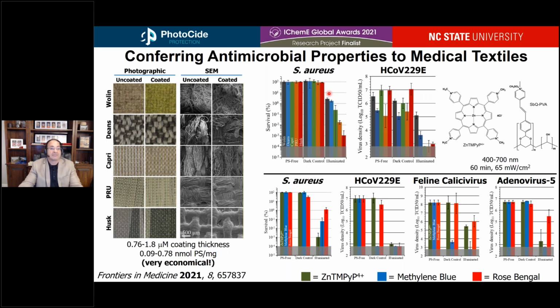As an example, against Staphylococcus aureus, a gram-positive pathogen, we're able to, depending on the material, obtain anywhere from 97 to 99.999% inactivation of the pathogen. Against human coronavirus strain 229E, again, a common cold coronavirus that's very similar to the COVID-19 coronavirus, we're able to achieve 90 to, again, 99.999% inactivation of human coronavirus. The studies in the top panel were done using this porphyrin-based photodynamic agent. However, we can use commercially available photodynamic agents that are scalable at the needs that are necessary for deployment in hospitals or other consumer marketplace products.